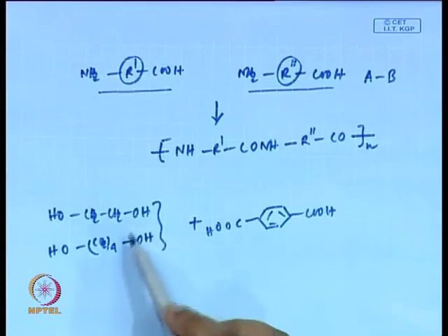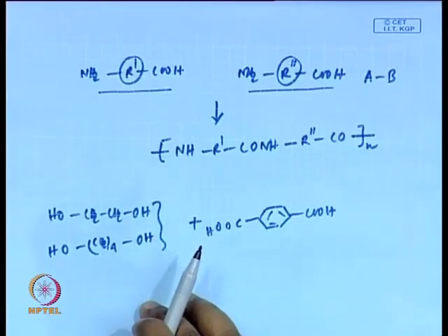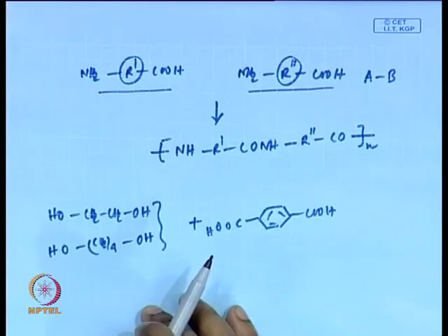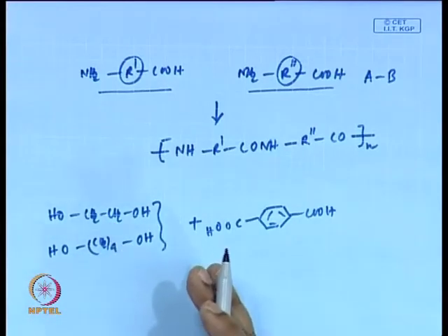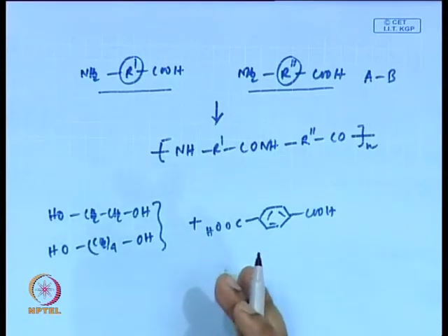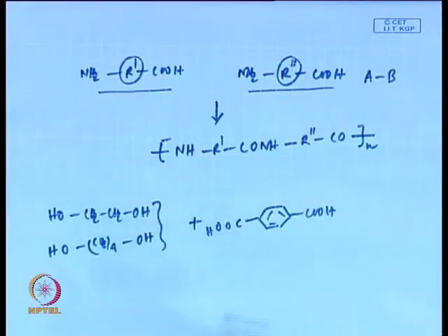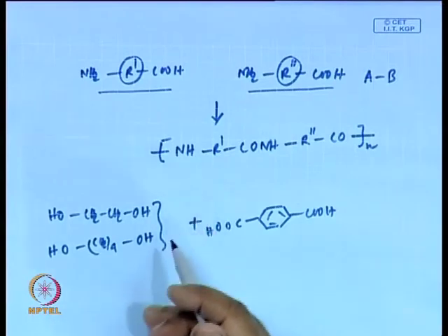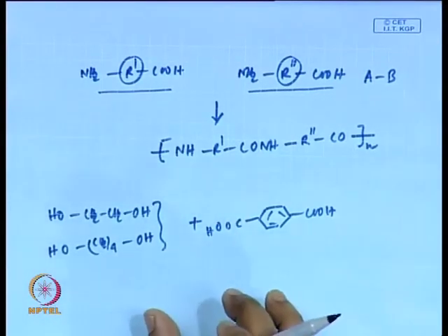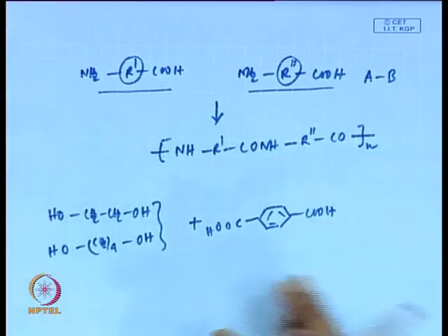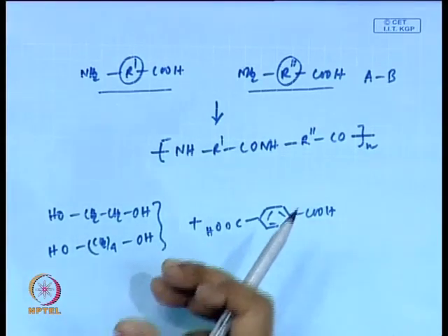Now, in the normal step polymerization reaction, because this goes through a thermodynamically controlled process, the byproducts also take part in the reverse reaction and the intermediate chains also take part in exchange reactions between them. So, they reshuffle all the time; during the entire reaction there is always reshuffling happening between the chains.